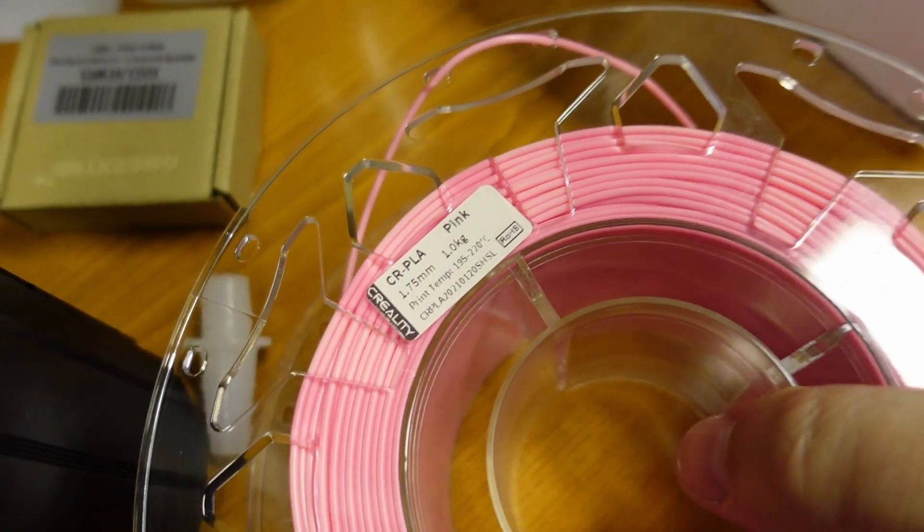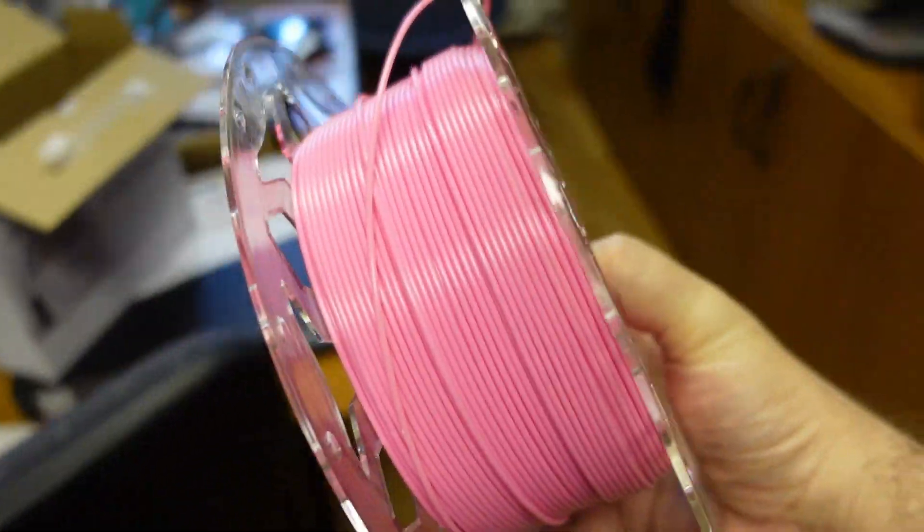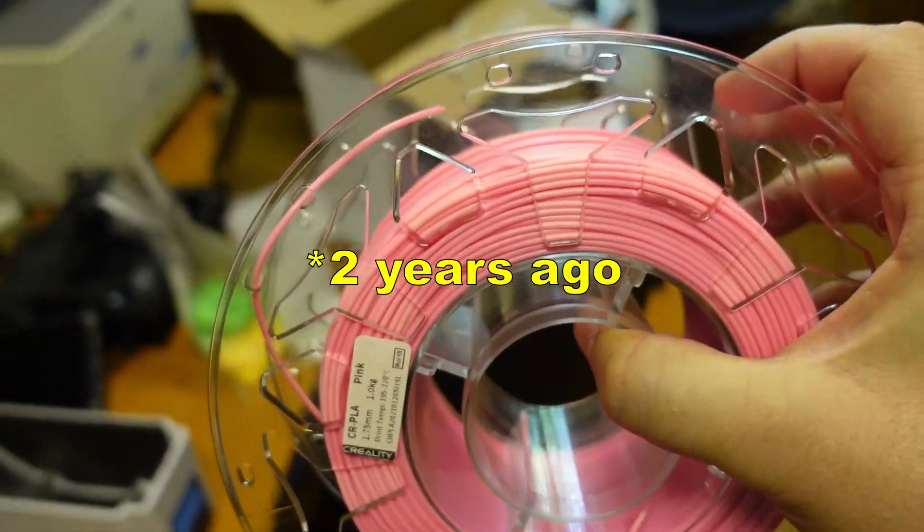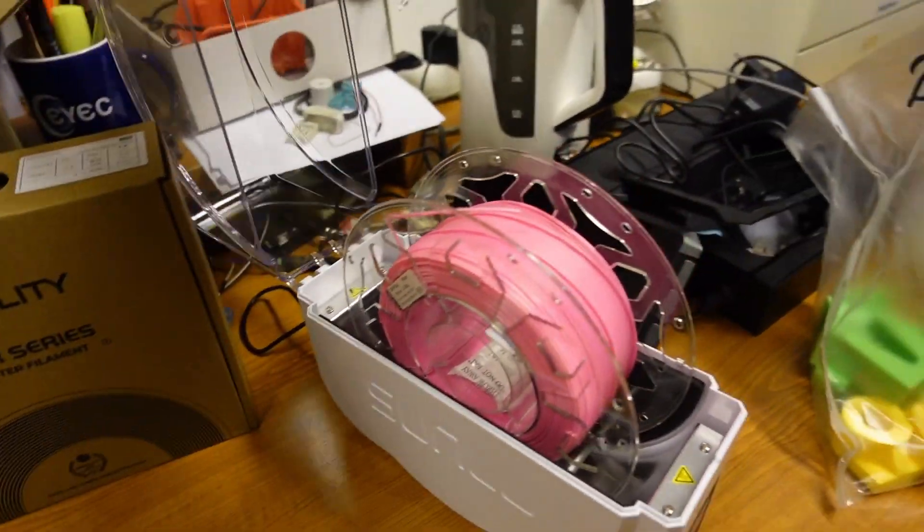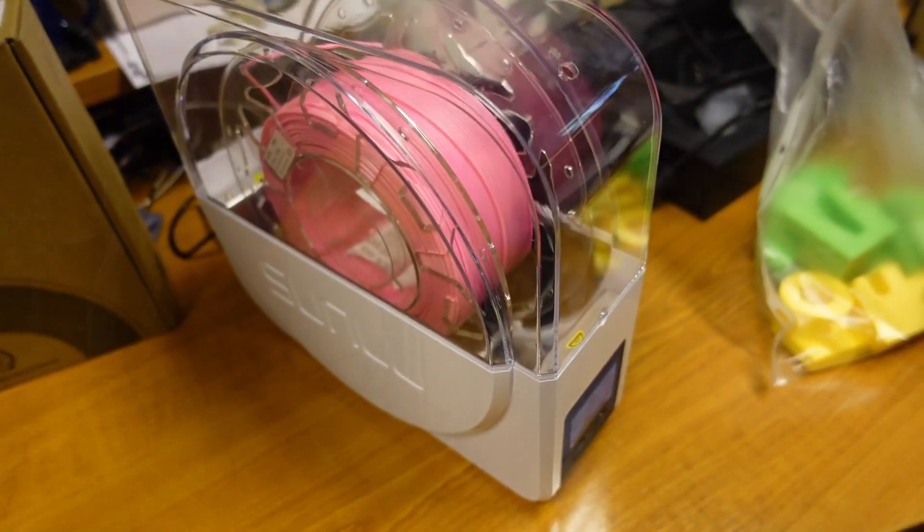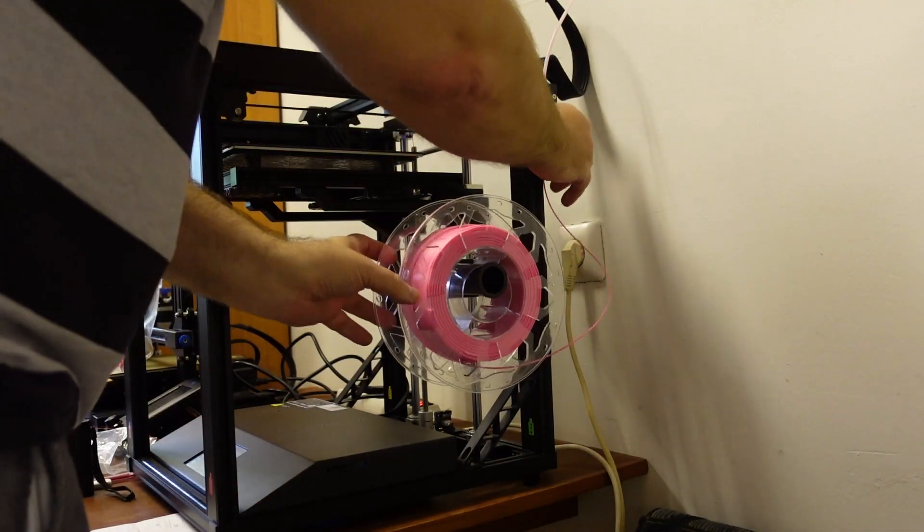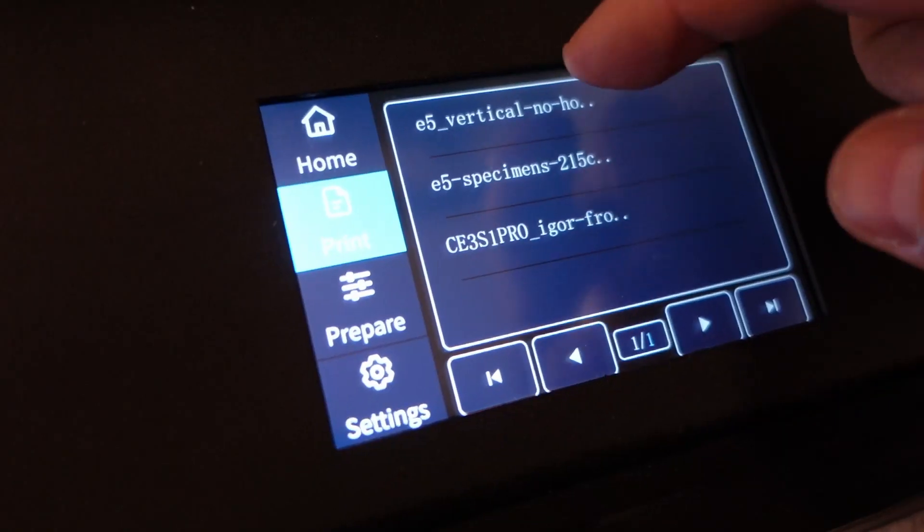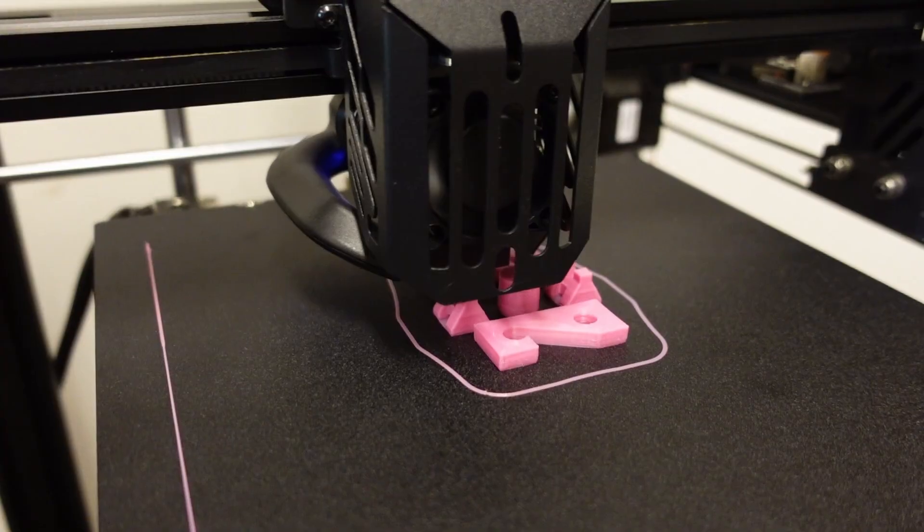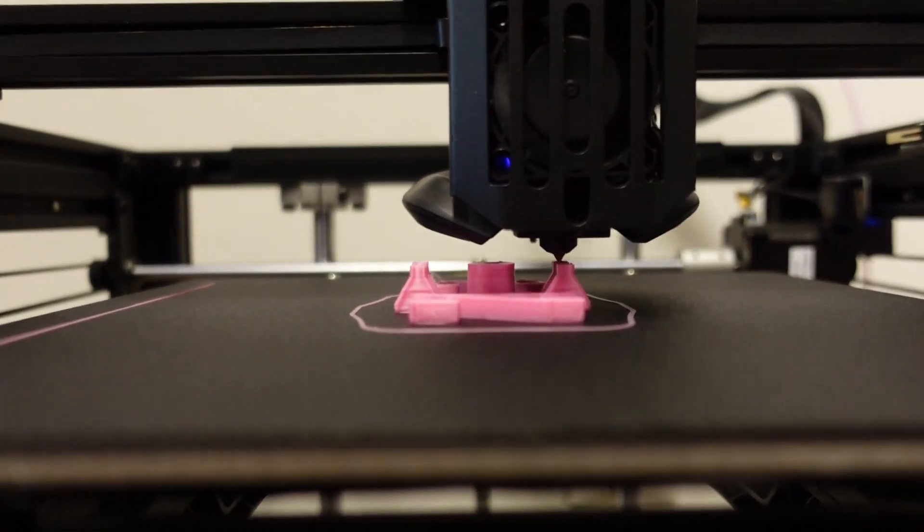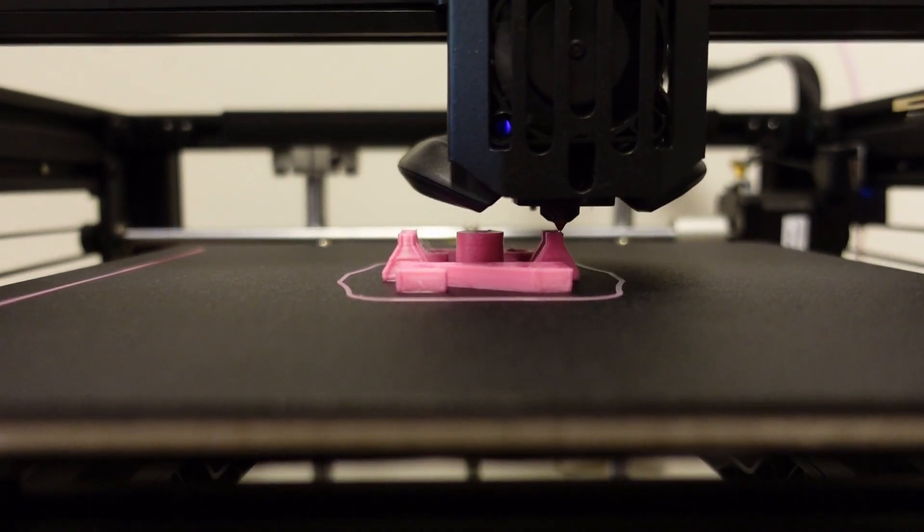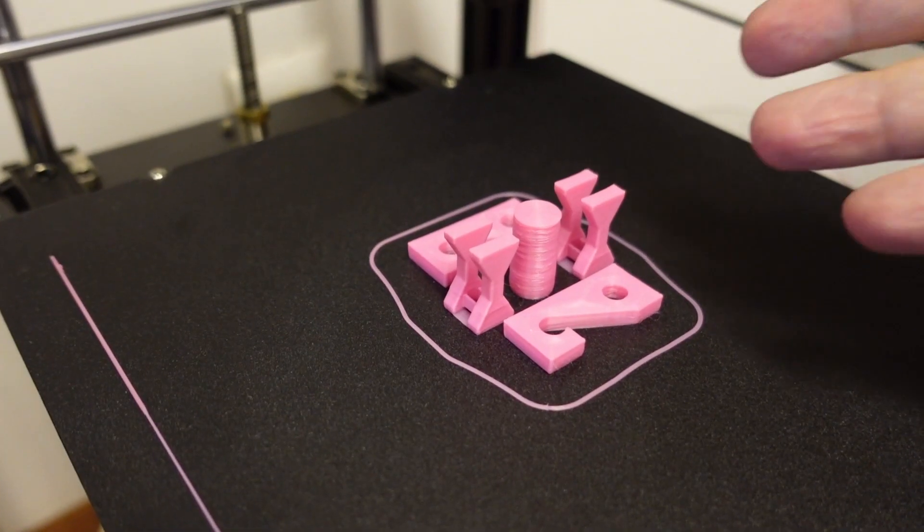All test objects are printed from this Hyper PLA. This is CR-PLA, the only Creality PLA filament currently I have and I opened it maybe more than a year ago. So just in case I dry it here two hours on 50 degrees Celsius and I will reprint those test objects for the layer adhesion test and the test hooks. I will use the same G-code like previously with the Hyper PLA. Visually I cannot see any difference during the printing between these two materials.